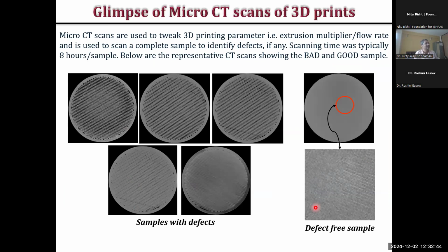So once we design a material, we manufacture it, we take a micro CT. No doubt, scanning electron microscopy is another instrument which is readily available, but I get better and more intricate details in micro CT. This is the same micro CT which doctors use for any advanced investigations when we have a bone fracture and so on and so forth. So I have just shown with defects and without defects. So from this to this, we tune up the manufacturing process.